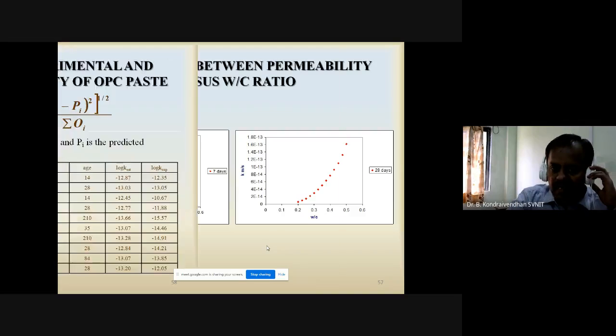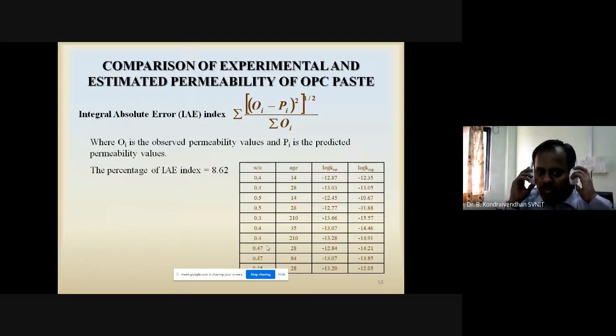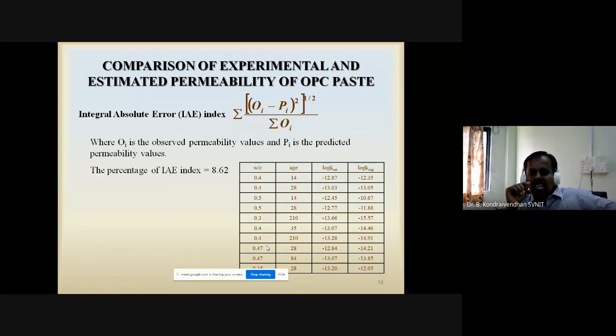And again, we have done validation also. For that, we have taken the integral absolute error index. By using this formula, we can calculate the percentage of the IAE index, where Oi is the observed permeability and Pi is the predicted permeability value. The IAE index is coming 8.62. If it is less than 10, it means it is correct. So it is valid. That's how we validated our work also.